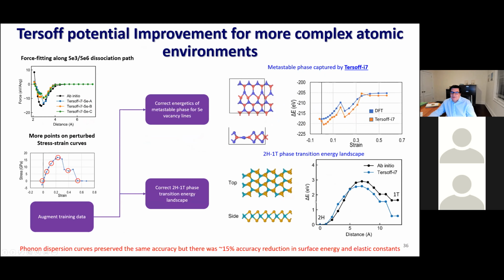So we corrected for this by using additional fitting of DFT data. And the message, without going into too many details, is that the force field is as good as the variable that you have included there, with the trade-off I mentioned. So if you are particularly interested in other properties, you need to very carefully check and most likely include them in the parameterization.